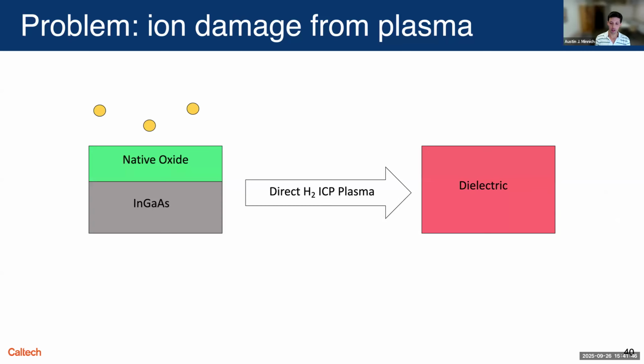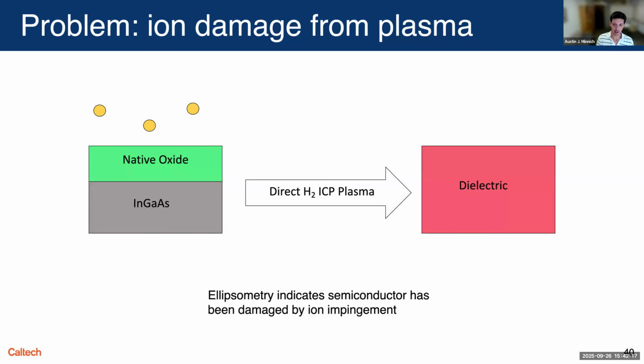All right, so we were trying to do this in an Oxford ALD chamber with a plasma on it. And in the first effort, we simply exposed the chip to the ICP plasma. And what we found from ellipsometry is that the semiconductor was basically getting converted into something else that was not a semiconductor. It was more of a dielectric with a different refractive index. So the key electronic component of the material was damaged. And we attributed this to ion impingement.